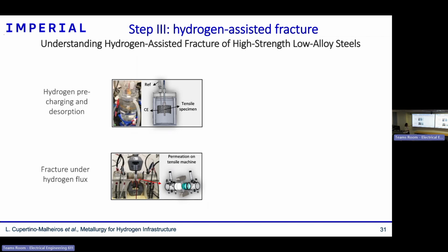Okay, so in this first work, I designed these two experimental methodologies to be able to separate the effect of trapped hydrogen only on the fracture and the effect of hydrogen flux on the fracture. So starting with the first one, what I have done is pre-charge some steel samples, tensile specimens that I can later use for the tensile test that I showed in the beginning, and let the hydrogen diffuse out in air. So I leave it basically on the desk, let the lattice hydrogen diffuse out, and I just want to evaluate the contribution of the trapped hydrogen to fracture.